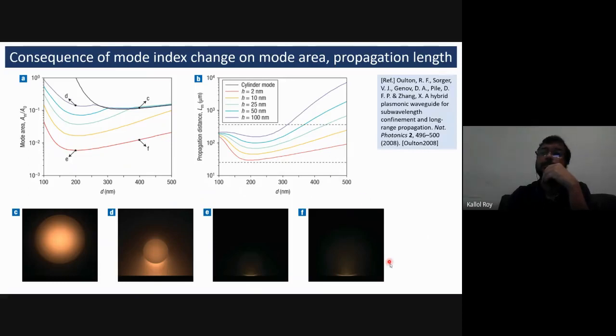And what is the consequence of this index change? You can see it over here. If you look at the bottom images, when the dielectric cylinder is placed much above the metal, all the light is inside the dielectric, whereas the moment you place it near the metal, light interacts with the metal and gets focused. And you can see here in this image, light is mostly residing inside the metal dielectric interface.